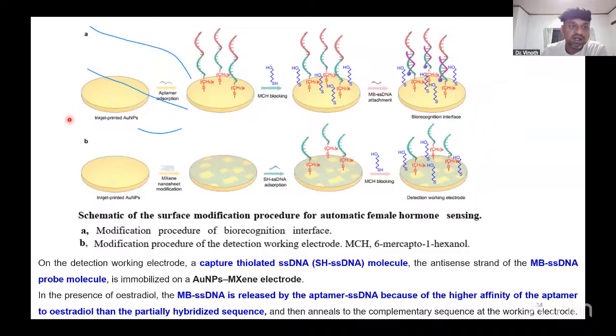This is the simple mechanism showing how the aptamer is located and reacts at the electrode surface. These are the inkjet-printed gold nanoparticles. Once we drop-cast the aptamer, it forms the Au-S gold-thiol bond with the thiolated aptamer, and then MCH blocking, mercaptohexanol, is used to block the unreacted active sites of the electrode surface.